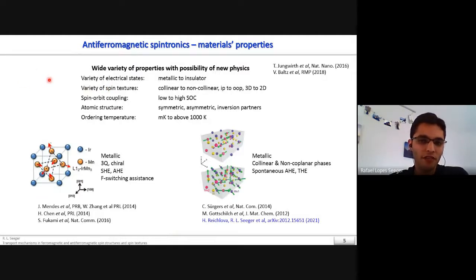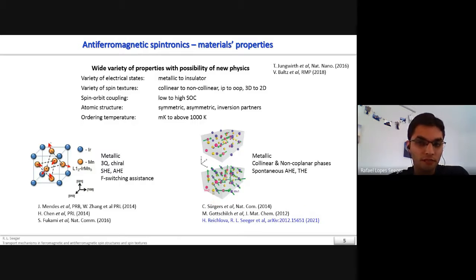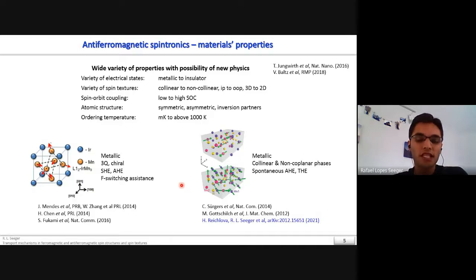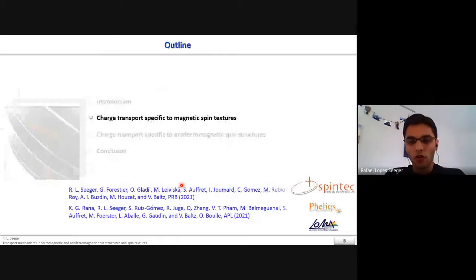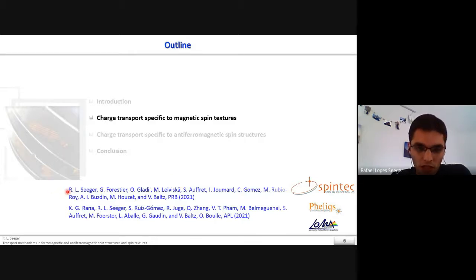With the perspective of spin-dependent transport in mind, anti-ferromagnets present a wide variety of properties that open multiple options for studying spin transport. I will mention two materials I was mostly studying during my PhD: iridium manganese (IrMn), because it has a large high Néel temperature and a large spin Hall angle, and the metallic compound manganese 5 silicon 3 (Mn5Si3), because this material presents two distinct magnetic phases with collinear and non-coplanar spin structures depending on temperature.